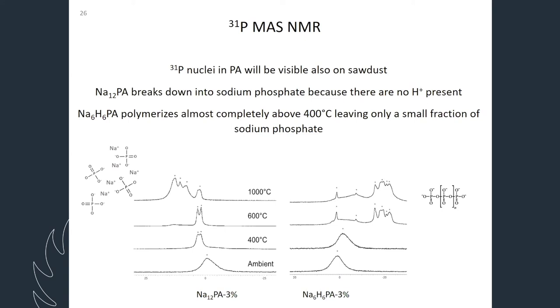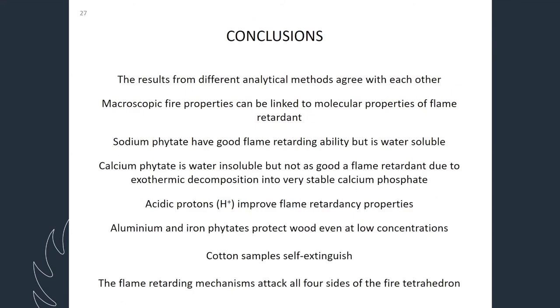So if we then continue to the conclusions and try to summarize this, we can see that we have used different analytical methods, and the results that we get from them agree with each other, so we can use them to explain the same things. And we can see the macroscopic fire properties can be linked to the molecular properties. Sodium is a good flame retardant because we could see that it forms those polymers that take heat away.